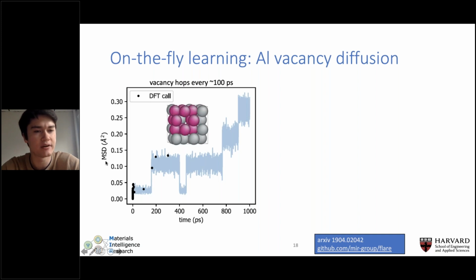What I'm plotting here is the mean squared displacement of the system as a function of time. Every time the vacancy makes a hop, you see a sharp change in the MSD. So basically the model is correctly modeling how the vacancy moves around. Every few hundred picoseconds or so, the vacancy makes a sharp hop, and you can see that happen over a nanosecond timescale. That's how long we ran this particular training simulation.